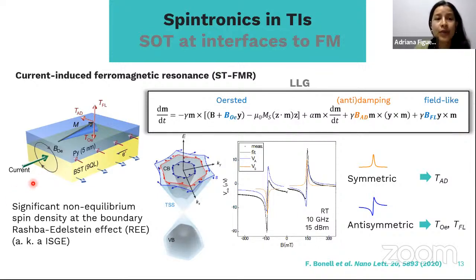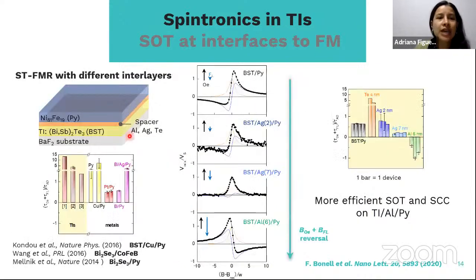But what happens is that, when it's well established that you have such interfaces of the TI with a permalloy, or with a ferromagnetic layer, you usually have interdiffusion, or these interfaces are not perfect. So what we did was perform this spin orbit torque study for different spacers between the TI and the permalloy.